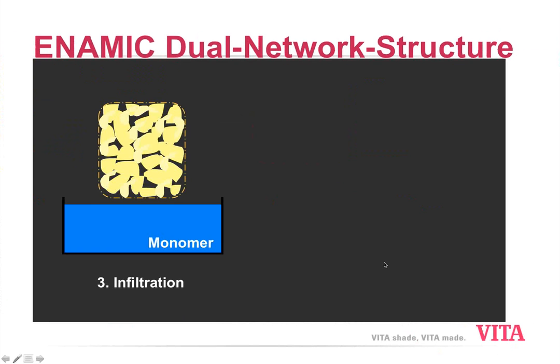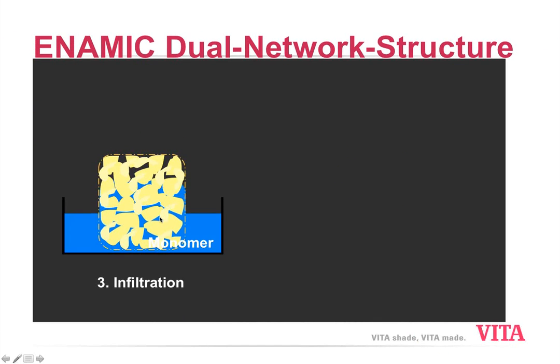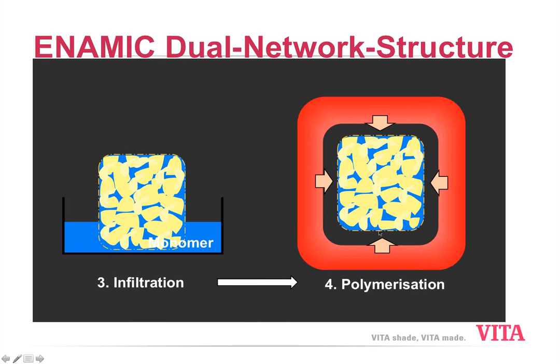So we have this porous ceramic sponge network. It's then placed into a monomer material. The monomer goes into the pores, completely fills all this porosity, and then it's cured under high temperature, and we have a chemical bond between the ceramic network and the polymer network, and we have all this material interconnected.